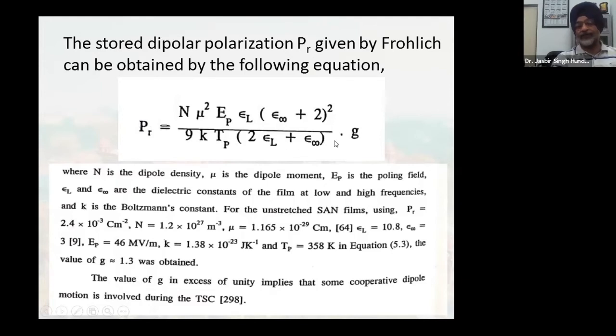We found that G was equal to 1.3 in case of unstretched films, SAN films, and it was around 2 for stretched and poled films. So the values of G higher than 1 indicate that there was a cooperative dipole motion within these SAN and ABS films. So that was that. Now this equation was given by Frohlich. This is what we used to find out whether cooperative motion of dipoles is occurring or not.